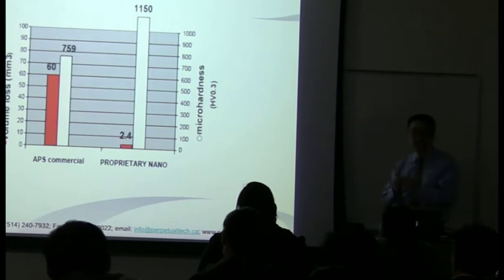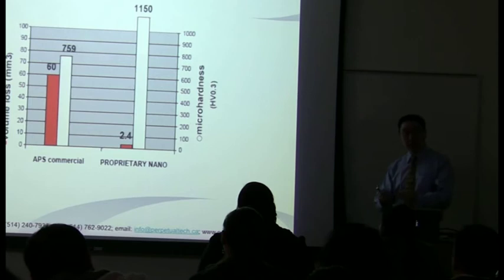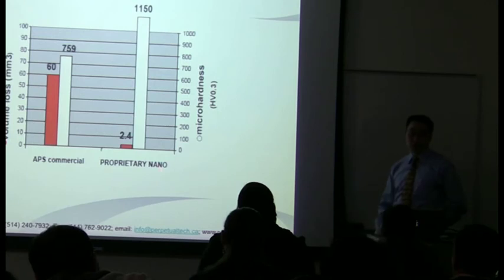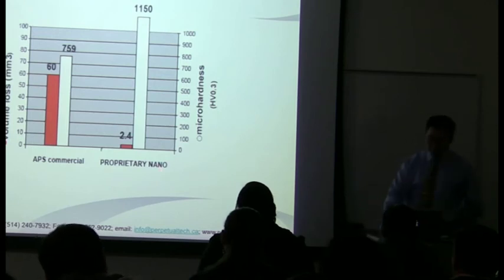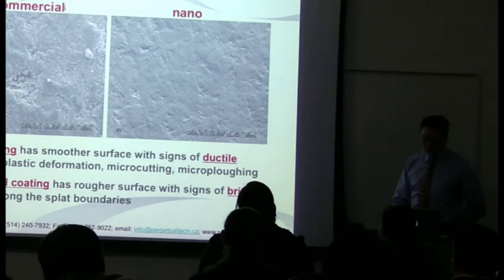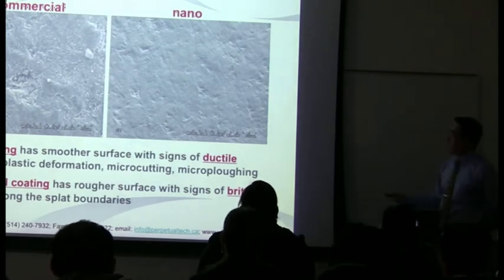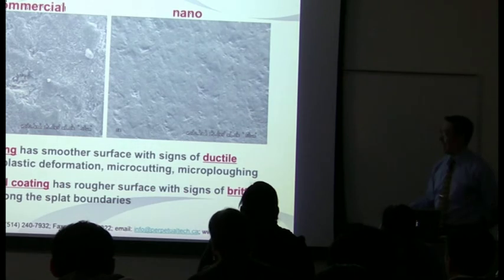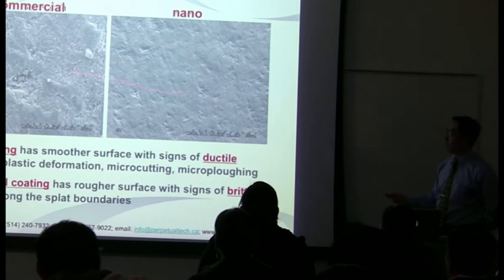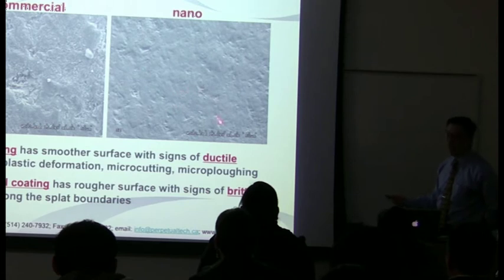But it's because you're increasing toughness in addition to the hardness or strength that gives you a huge drop in volume loss. And this is great. This is something that we did at McGill years after we carried out all those tests. We decided to look at the wear scars under the microscope. And this really validates the fact that we had a tougher coating.